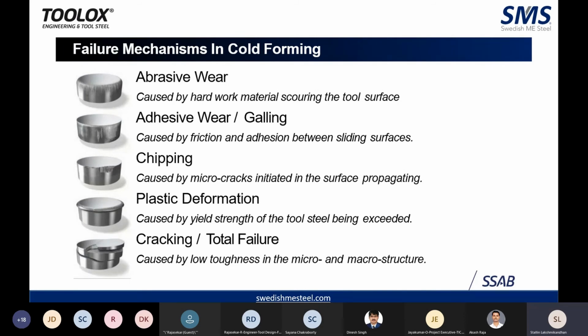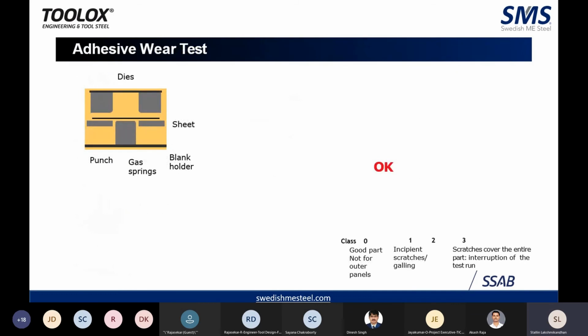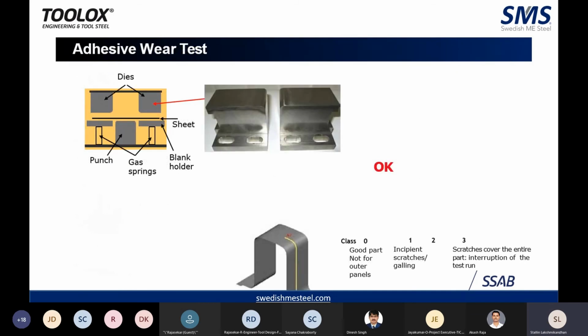If you have any cold working tool steel right now where you face an issue of cracking, Toolox 44 can immediately replace it. Because Toolox 44, as we had already discussed, comes with not only high hardness but also higher toughness. This higher toughness helps you resist cracks, both at the micro level as well as the macro level. This is the adhesive wear test just been done.